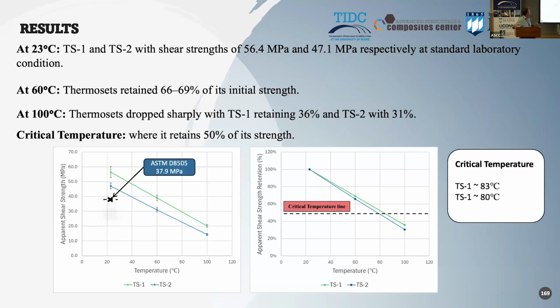Next. And what we have done here is we look at how the apparent shear changes with temperature. It goes down as expected, okay? That is what happens. Remember, these polymers had a TG of 100 degrees C. So here is where we have that kind of cliff. I mean, where properties will go substantially down, okay? What we're trying to do here is to look at what properties we retain at different temperatures and try to come up with performance requirement. So for example, we can define a critical temperature where we retain 50% of the strength, okay? And that is independent of the polymer system. That's what we like to see in the standard.